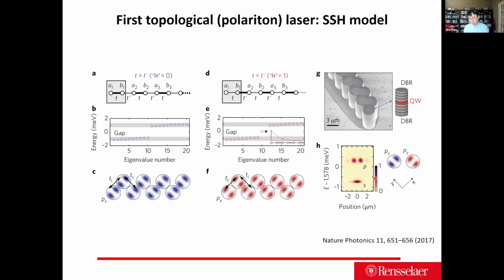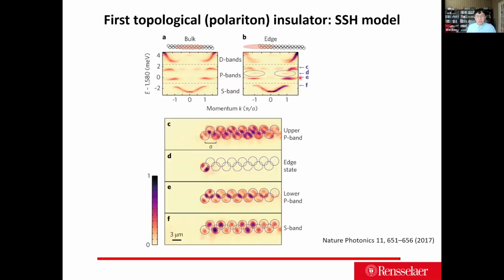The work has been demonstrated by Professor Jacqueline Bloch. You can see they etched these very hard to etch quantum well pillars, about 3 micron in size. And one can demonstrate this localized topological edge state. As you can see here, this is the topological mode, and this is the topological edge state they show in the paper once this topological mode starts to be excited.